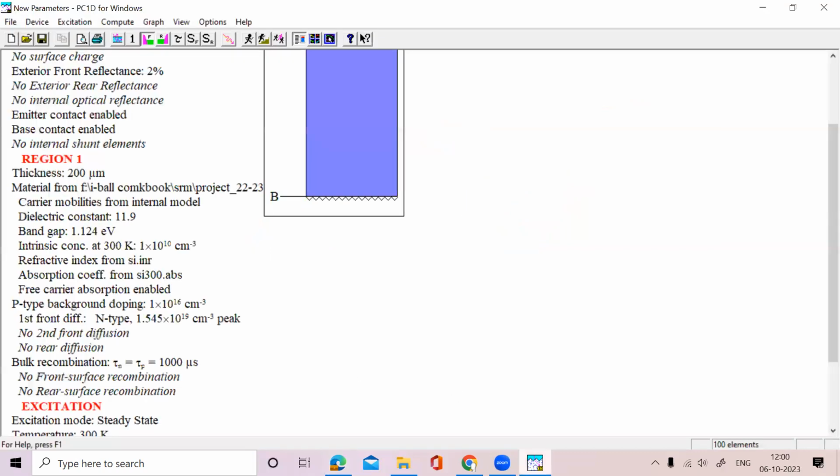So it is very tough to do practically. To optimize the silicon nitride thickness in my lab, I needed 1.5 years. Just the silicon nitride thickness of 75 nanometers was achieved after 1.5 years of work. So this is a little bit challenging.